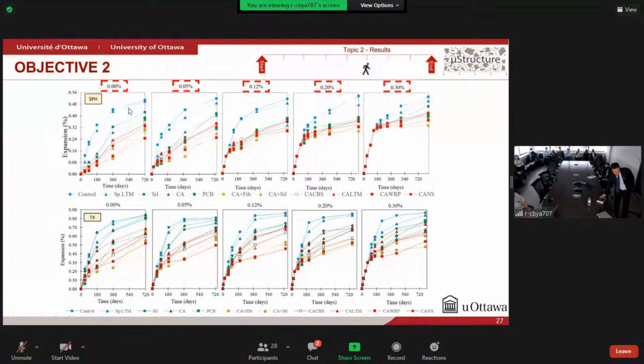I would like then to compare the results from 0% of expansion, once we apply the different treatments at this point, with those in which we apply the different products at 0.30% of expansion. Why would I like to do that? Because as we can see, and I would like you to save this information because it's important, the higher the initial damage of the concrete, it seems that the different surface treatments are more effective to reduce residual expansion in the concrete. This is a weird behavior, but I would like you to save this information because it's going to be important after.